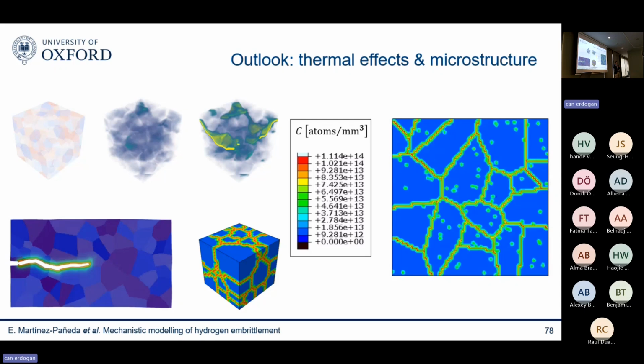These are continuum level tools, so you can extend them. You can use them with crystal plasticity. You can use them with new theories that we have to capture segregation to grain boundaries and cracking. So they're suitable for those type of problems, at least CPFE type of calculations. And the other problem, again, I didn't want to show some data today, but still very much ongoing, is that everything that I showed you before was isothermal. We only care about hydrogen and isothermal conditions, which are typically the worst.